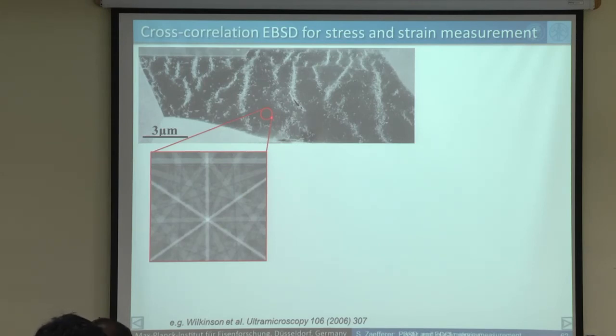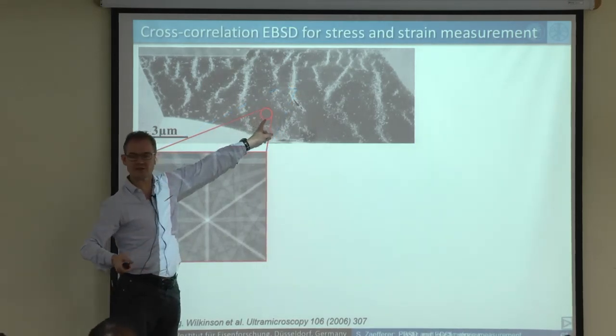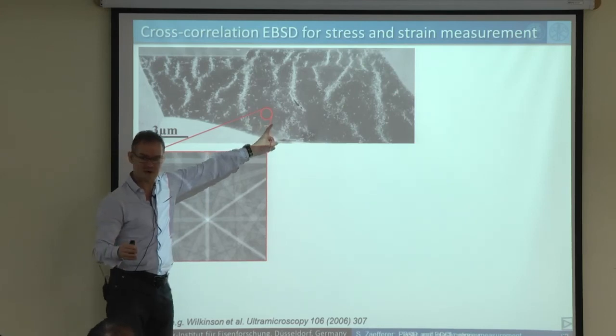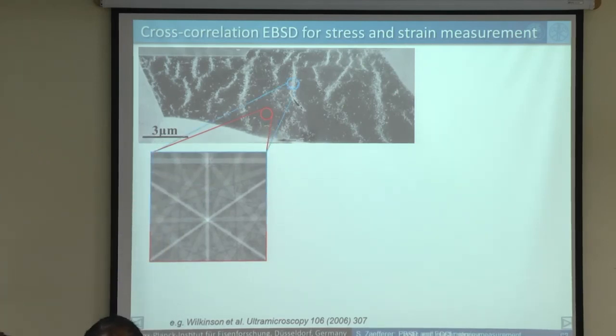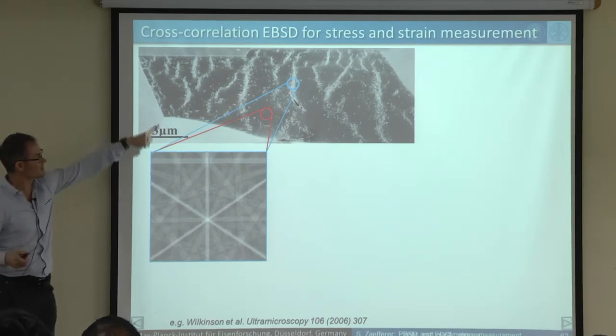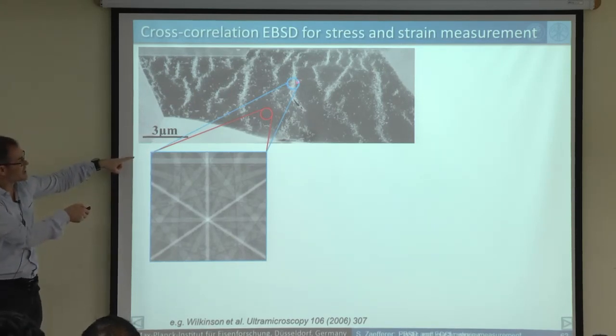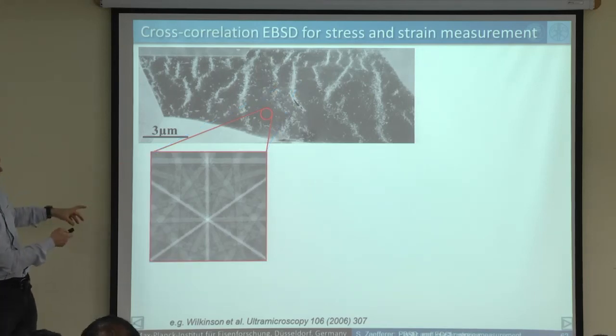So we take a diffraction pattern from this area here, and we take a diffraction pattern from an area which we want to measure, from which we want to know the residual stresses. This one here has been taken in an area where there's nothing happening. So we assume there is no stress. We take this as a reference. And this one is an area where we assume something has happened. And if we compare these two, we see that due to the elastic strains residing here, we see a change of the diffraction pattern.